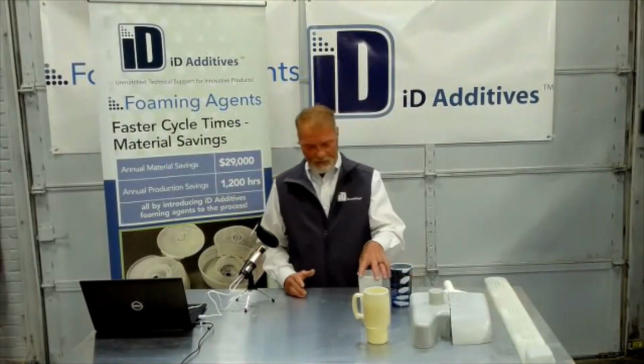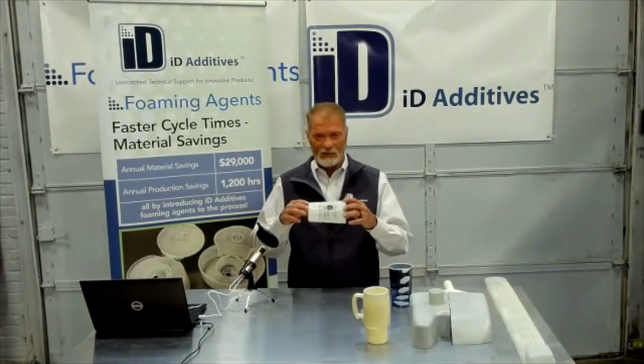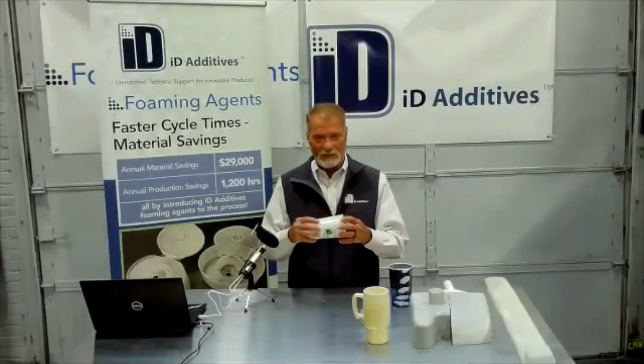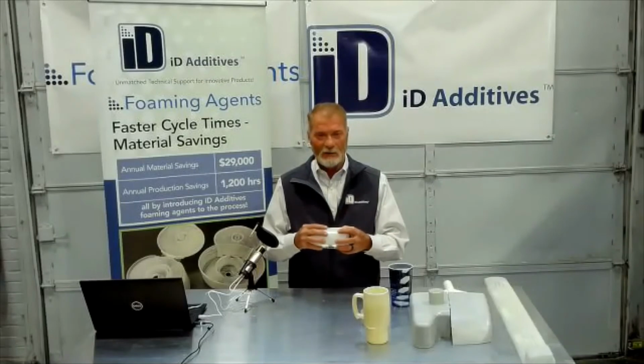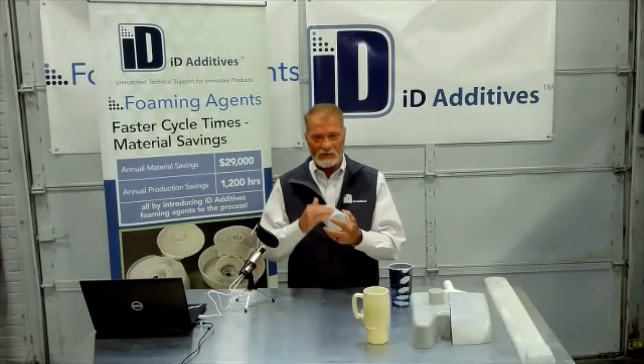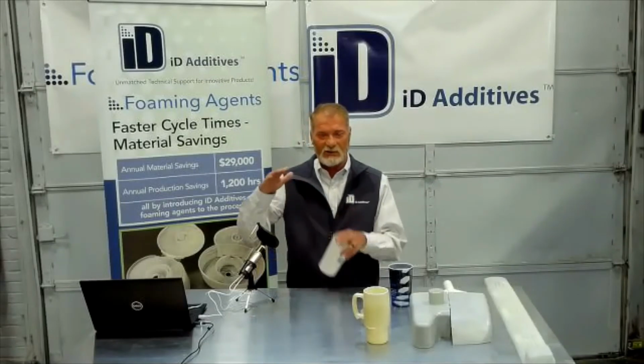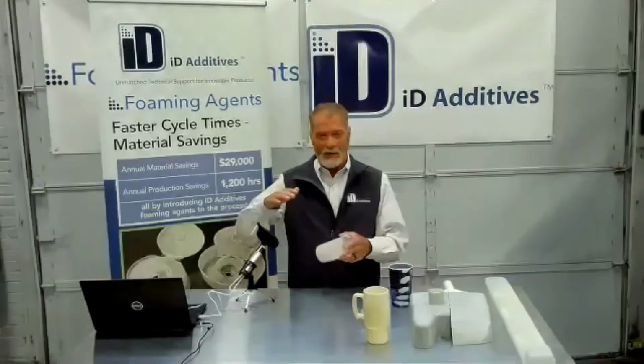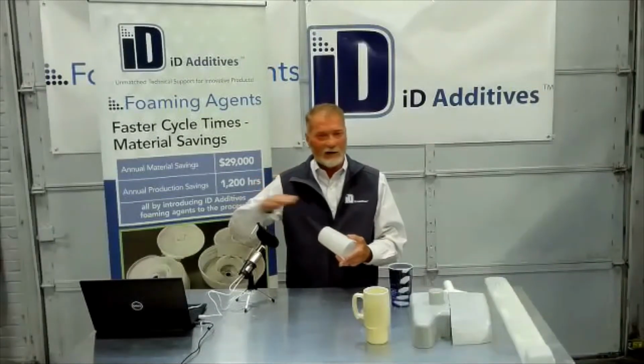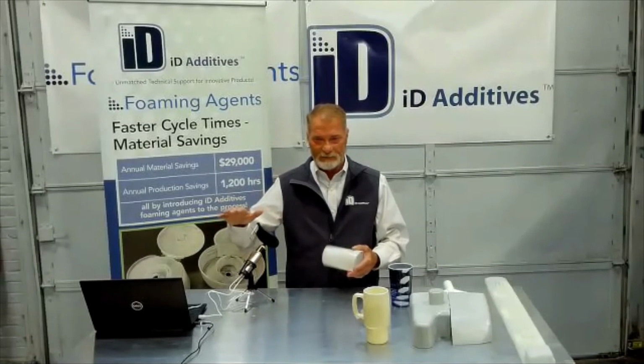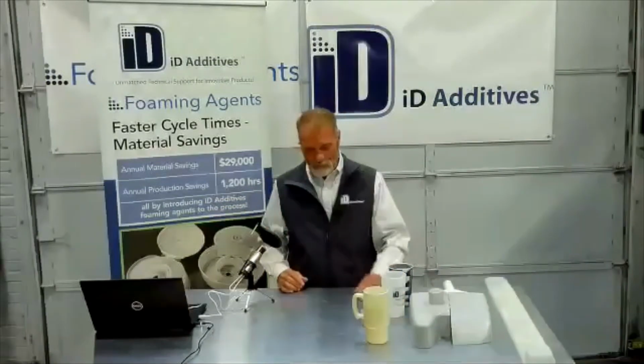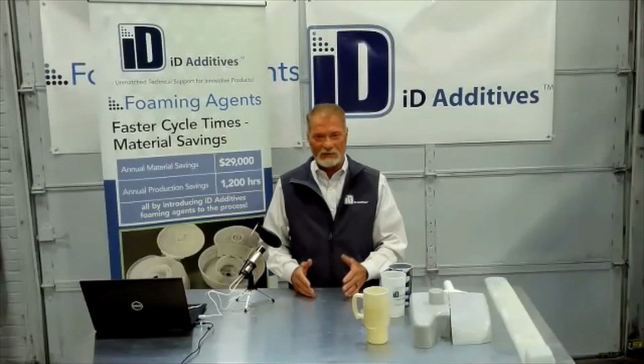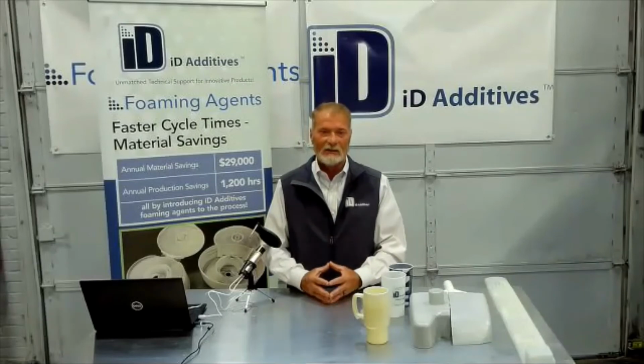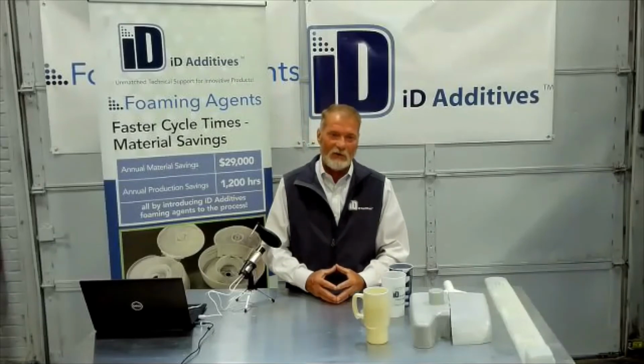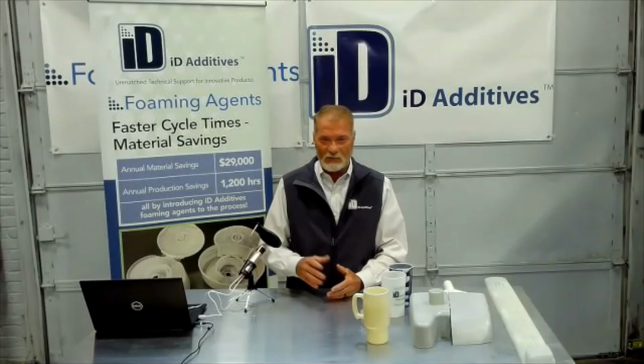Even with foam, you want to put in enough to get you where you want. Even in a wall like this, there's only going to be so many bubbles in this wall. If you try to add more, it'll push to the surface and you'll have splay. There's a certain point where any more foam is not going to do you any good. So you're only going to get so many bubbles in an aesthetic part. You try to go higher on the foam, chances are you're going to push it to the surface.